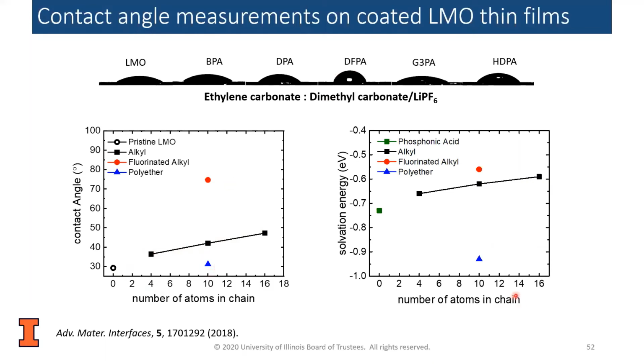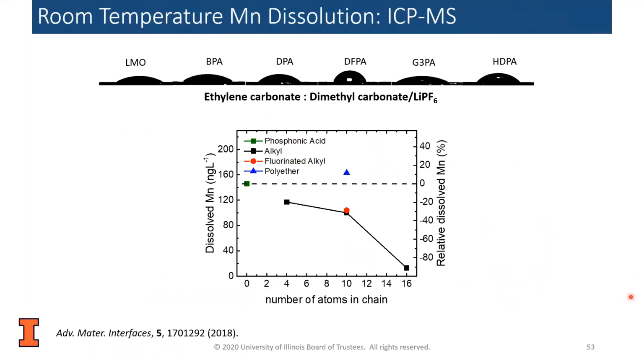And again, the polyether is the lowest because it is wetting very well. In this case, we're looking at the amount of dissolved manganese as determined by ICP-MS. We can see that the thickest alkyl chain, that is the one with the longest chain length, attenuates the dissolution of manganese the most.